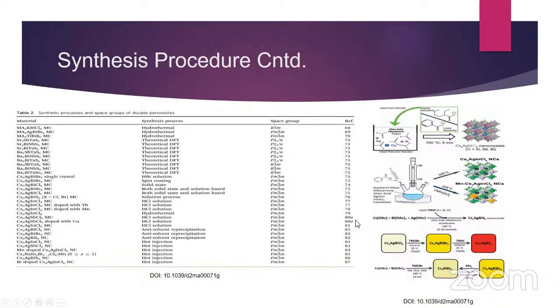And here I have mentioned some more processes to synthesize the halide double perovskite in microcrystal, nanocrystal, and single crystal form. In this diagram I have specifically mentioned the synthesis methods to produce double halide perovskite nanocrystals. The first one is the ligand assisted reprecipitation method, the second one is the famous hot injection method, and the third one is the anion exchange method. Here you can see we have started with Cs2AgBiCl6, and then all the chlorine atoms are exchanged, and we get Br6, and at the end we get iodine, that is I6.